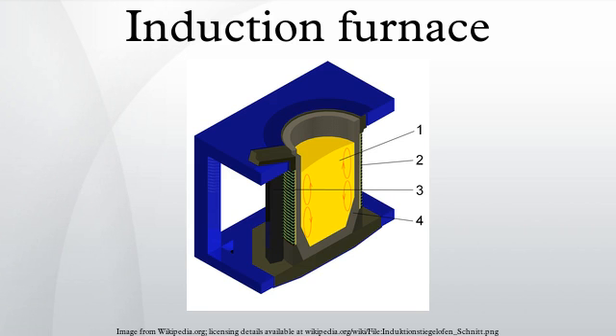The one major drawback to induction furnace usage in a foundry is the lack of refining capacity. Charge materials must be clean of oxidation products and of known composition and some alloying elements may be lost due to oxidation.